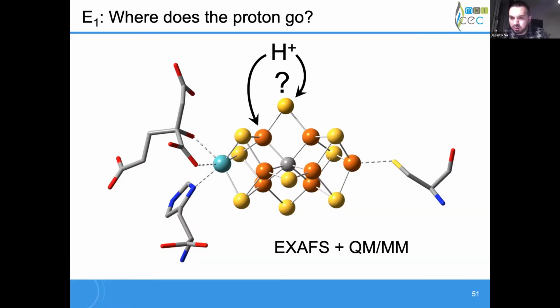And then the other one is, now that you know the energy range where there are differences, could you reduce the energy range of the HERFD scan to emphasize, for example, the pre-edge feature? In the HERFD scan, you still need to be able to normalize your spectrum. So in our HERFD scans, we're already focused.